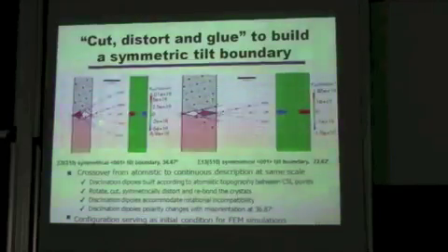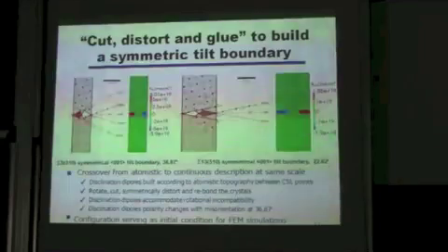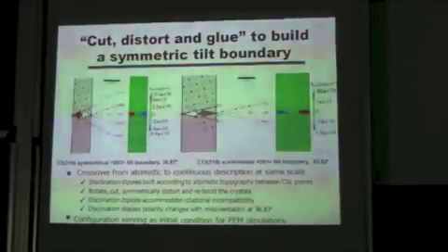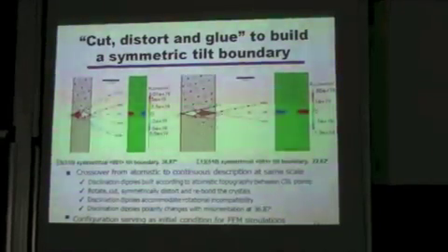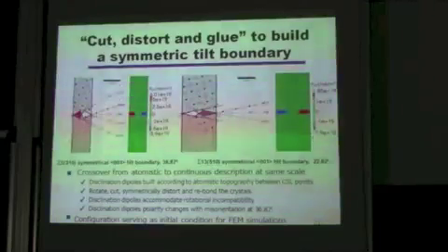Okay, so you have a discontinuity of rotation here, obviously. So these two lines are apart from each other, and you will glue them once they merge along the interface. And on the other side, there is a compression. So that means that you have a disclination dipole here.